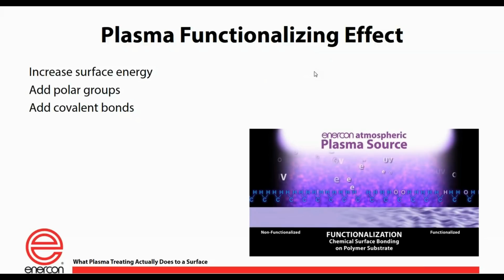Now we're looking at probably the most complicated of the effects that plasma or flame has on the surface, and that is adding the polar groups that were discussed in that video. You're adding these on a molecular level. You're changing the outermost molecular level of your surface, and it is adding polar groups. When you increase the surface energy and you do a dyne test on it, it's that polar energy that you're increasing. And the polar groups in that case are allowing you to have a better bond. Someone described it to me once as a Velcro on the surface, for lack of a visualizing term there. So you're actually putting those polar groups, and that is what gives you a more effective bond.